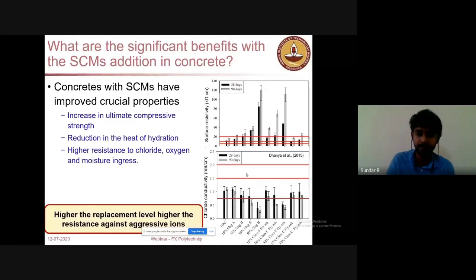If you add SCMs in these kinds of concretes, the durability improves. Concretes with very high additions of fly ash and slag, for example 50% slag and 30% fly ash, have very good resistance to chloride conductivity. The concrete with 50% slag and 50% fly ash has a very high resistivity to chloride. Also, for surface resistivity, the high-volume replacement of slag and fly ash stood alone, and even 30% replacement of fly ash gives very high resistance to the entry of these ions.